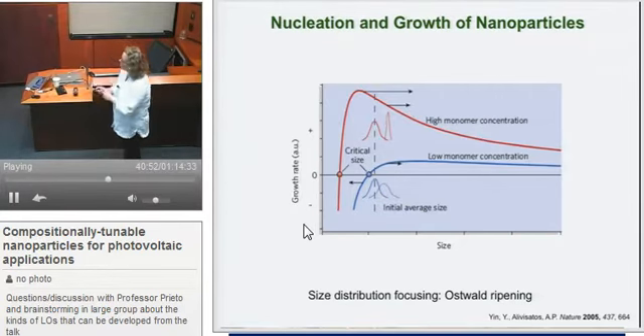But the idea is basically, if you think about size of your particle in a generic way and the growth rate, when you inject your precursors and they decompose and nucleate, if you have a very small particle, it can grow really fast, and then it depletes the amount of, we call it monomer, because we don't really know what's in solution. And then the growth rate is going to tail off. If the critical size, so what you need to nucleate to be stable, so it won't dissolve quickly, is larger, the growth rate's going to be smaller, and you get this. This is the case for low monomer concentration.